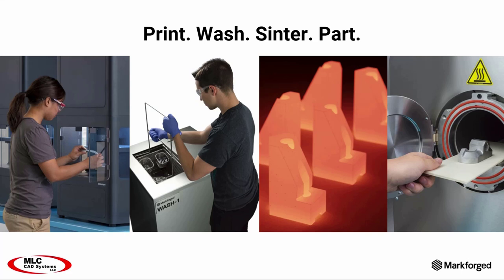The next step after your print is the wash. When the part has been printed, we're going to move it to the wash. This step is intended to remove the wax in the parts. The next step after your wash is going to be the sinter. First, the polymer is burned out of the part through the pores left behind with the wax removal. Then the metal particles begin to atomically diffuse together and create connections as the heat ramps up.